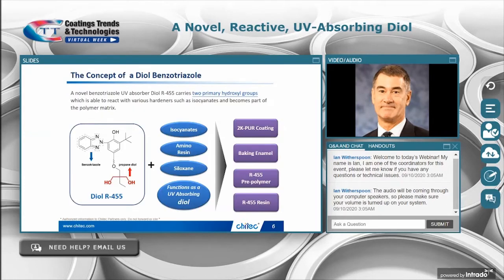And so here's the structure of the diol. And you can see down here two primary hydroxyls. And they react with a variety of common functional groups, like the isocyanates and melamines, siloxanes. The strategy here is to tie down the R455 during cure of an enamel, or the R455 can be pre-reacted into a resin during polymer synthesis. So either strategy works well. The benzotriazole ring has the usual excellent absorptivity, covering the whole terrestrial range of the UV spectrum from 290 to 380 nanometers.